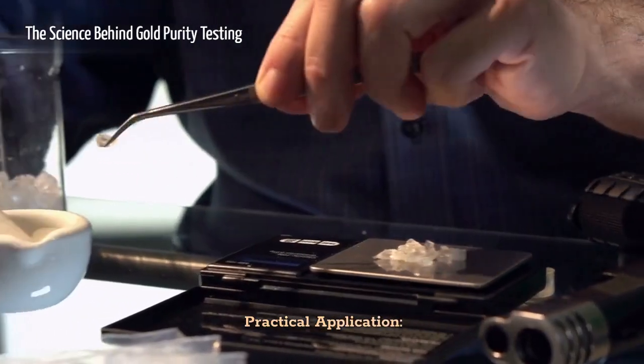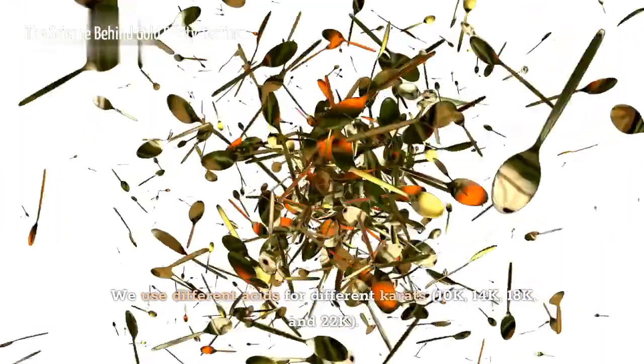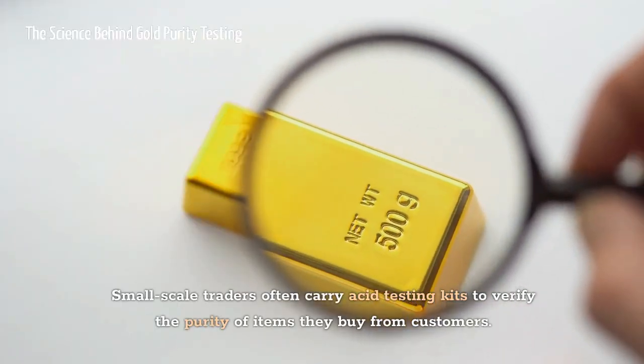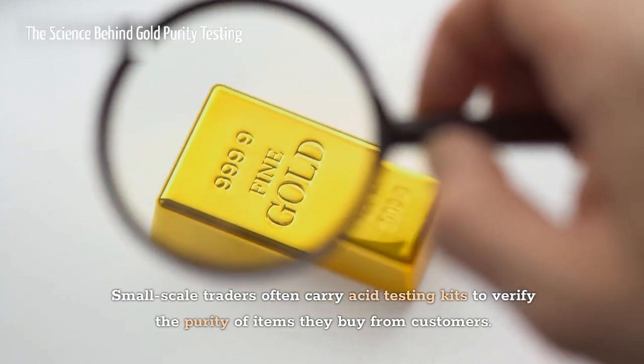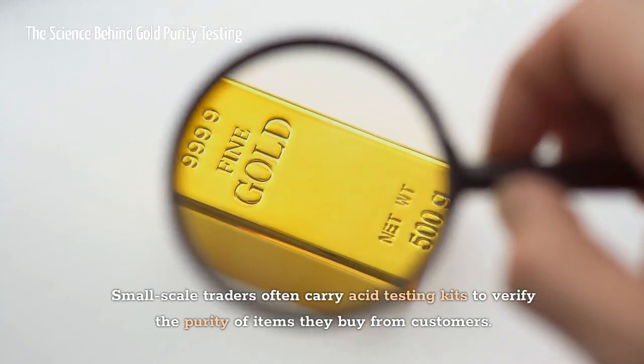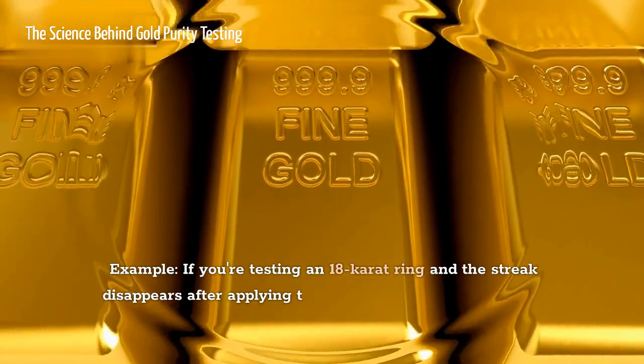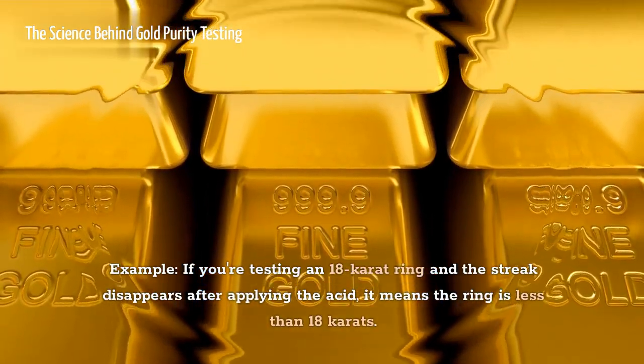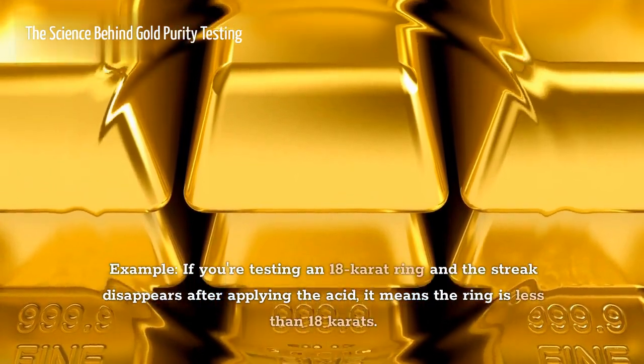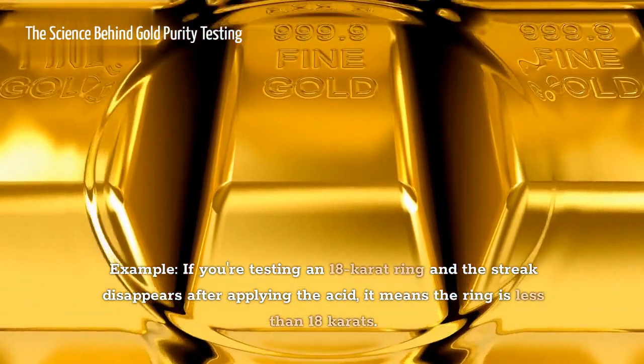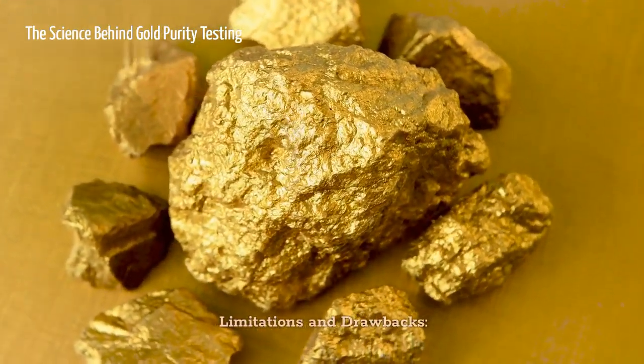Practical application. We use different acids for different carats, 10K, 14K, 18K, and 22K. Small-scale traders often carry acid testing kits to verify the purity of items they buy from customers. Example. If you're testing an 18-carat ring and the streak disappears after applying the acid, it means the ring is less than 18 carats. Limitations and drawbacks.